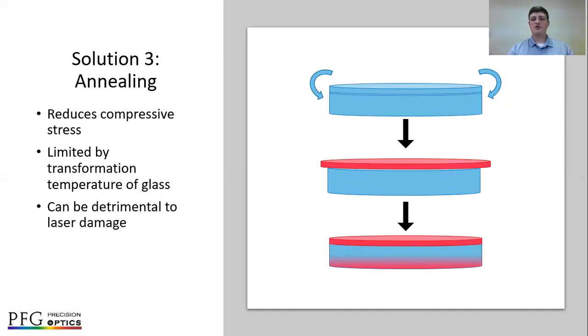Option number 3 is to do a post-coat anneal. As I mentioned before, thermal stresses almost always induce a tensile stress. So if you're using a high energy process such as IAD or sputtering that produces stress that's too compressive, you can do a post-coat anneal to drive that stress in the tensile direction, again with the goal of getting that as close to 0 as you can.